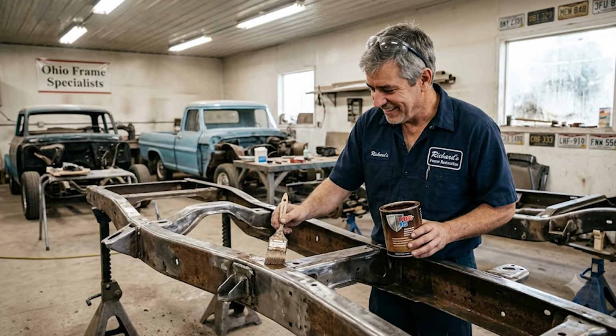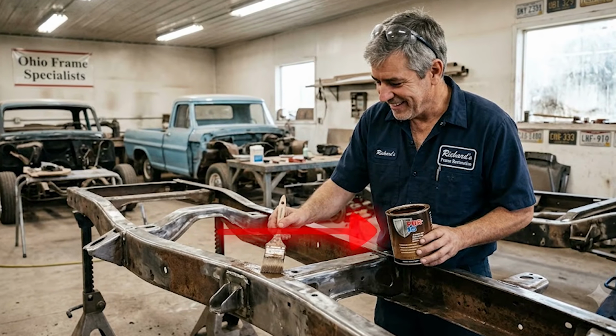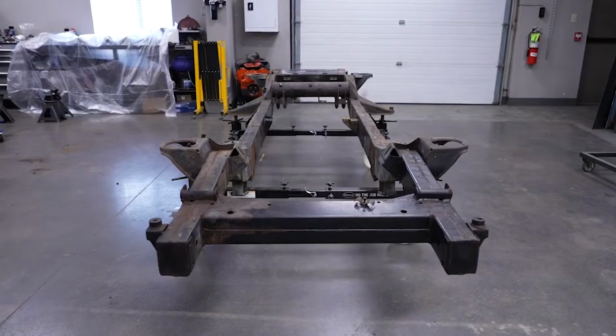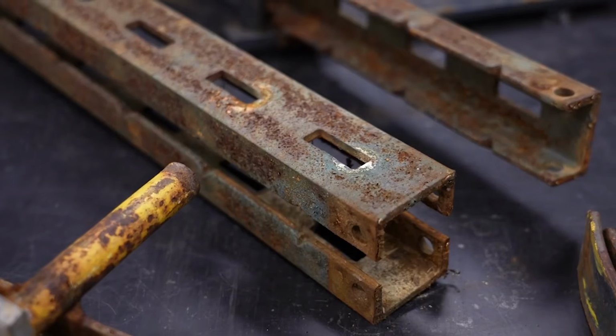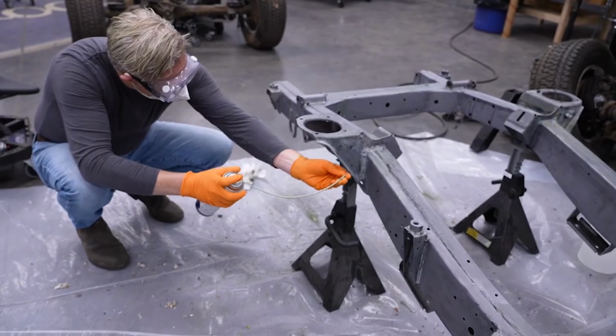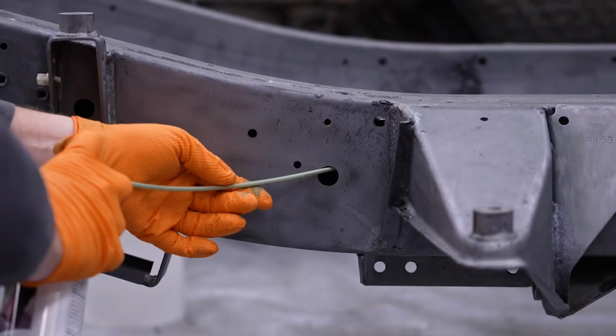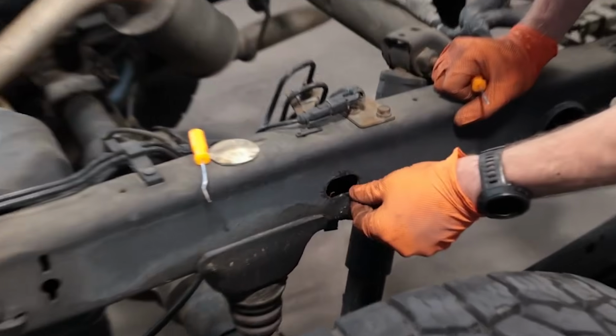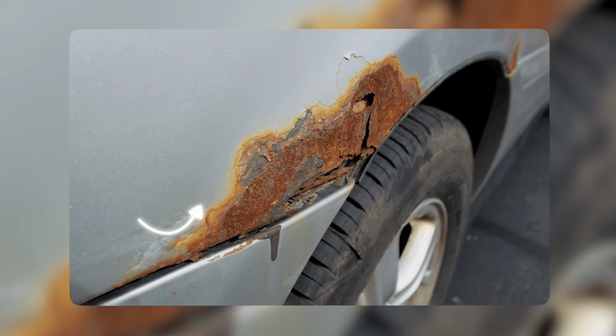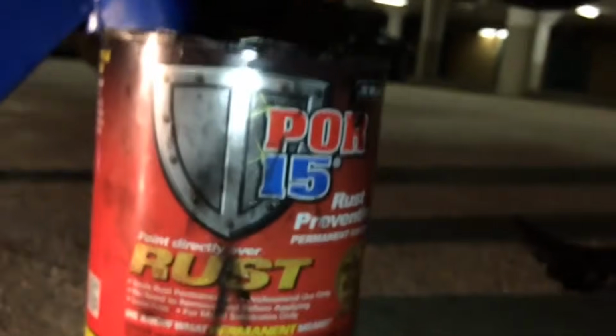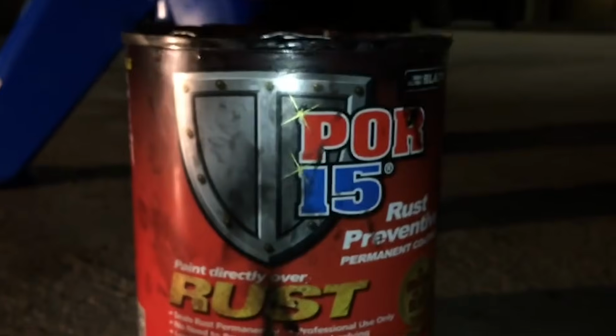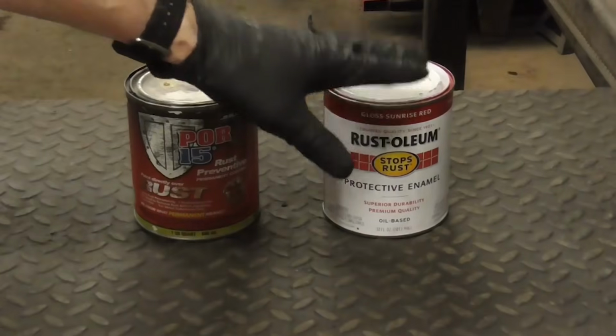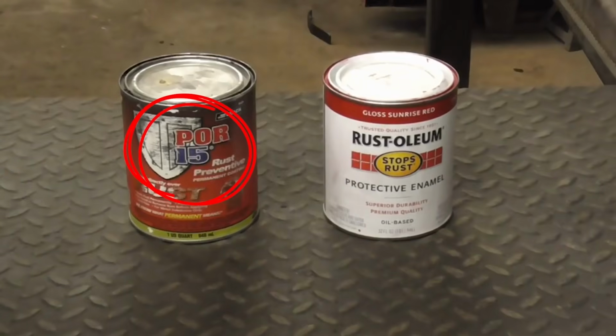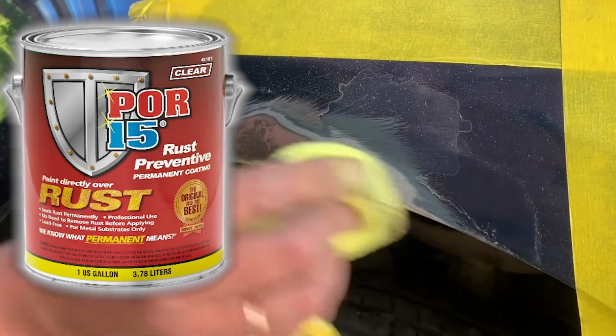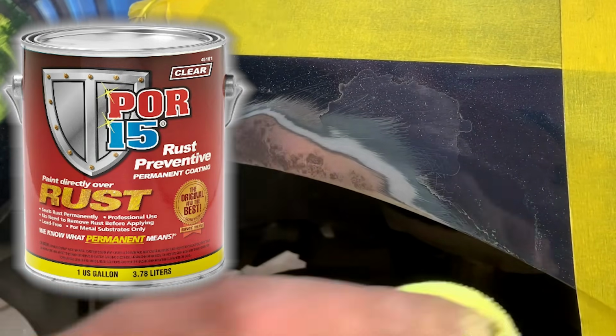A frame restoration specialist from Ohio named Richard has used POR-15 as his primary frame coating for 9 years on vehicles ranging from light trucks to commercial van fleets. He describes the product as the only coating he has used that he does not need to apply over bare metal to trust. He can apply it over mechanically cleaned rust and achieve results he is confident enough to warranty to his customers. Richard's warranty period on POR-15 frame treatments is 3 years. In 9 years of applying this warranty, he has had 2 warranty claims. Both were traced to inadequate mechanical preparation before application, rather than product failure.